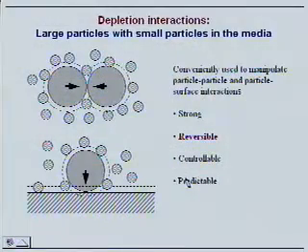Now you can say, okay, again, how does this relate to practice? This is how it relates to practice. If you take two latex spheres and you put something small, and this something small can be, in the simplest case, just micelles. So you make a very dense micellar solution. You put two spheres and suddenly you find that the spheres start sticking.